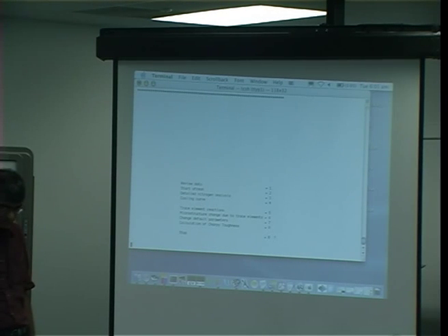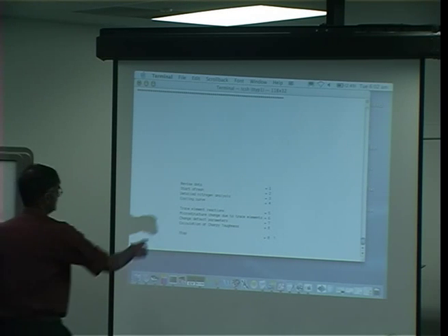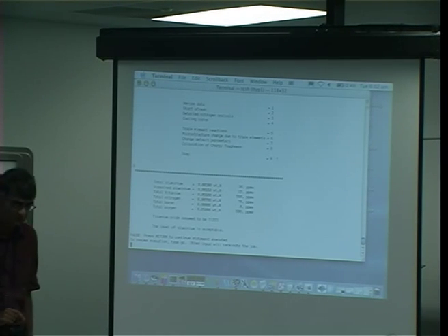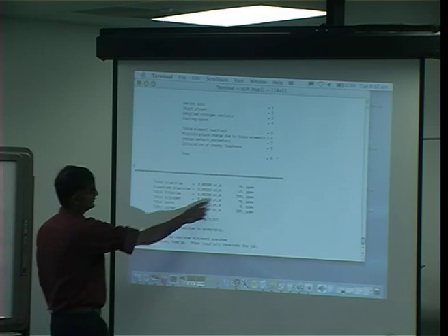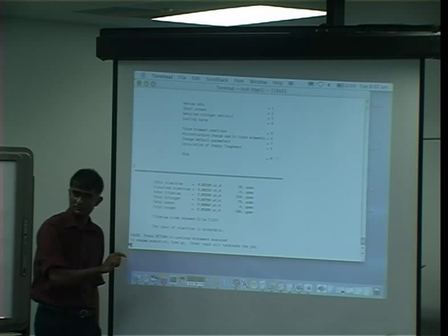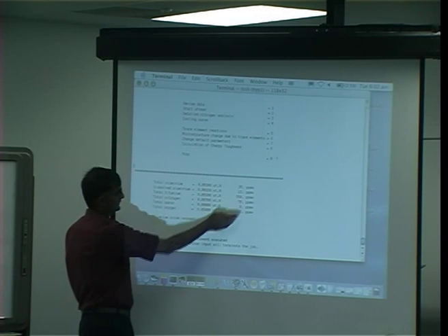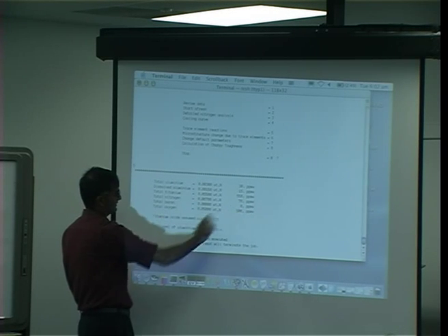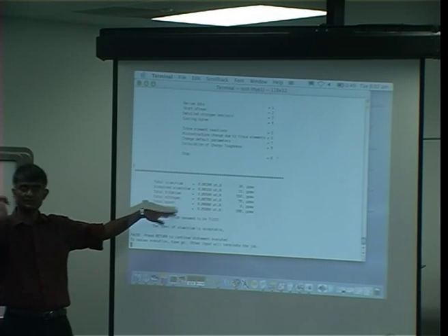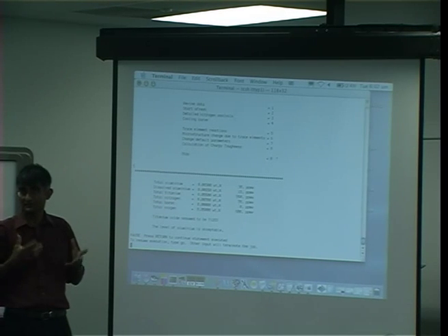And if you want to examine it, it will change aluminium, for example. So I was just going to say, if we want to examine the effect of trace elements, for example, trace element reactions, because those are important, then we can do that as well. So look, according to the inputs we had, the total aluminium is 30 parts per million, of which about 15 should be dissolved. And total titanium is 550. Total nitrogen is 70 parts per million. Boron is nothing. And oxygen is 500. This becomes interesting also if you add boron, because boron interacts with nitrogen.